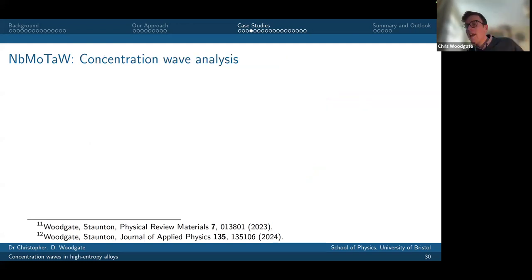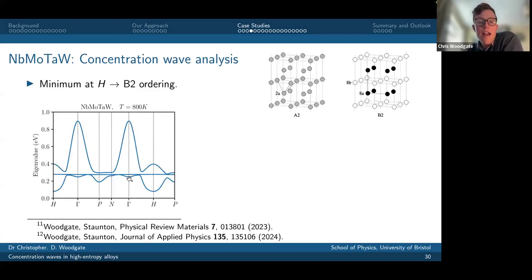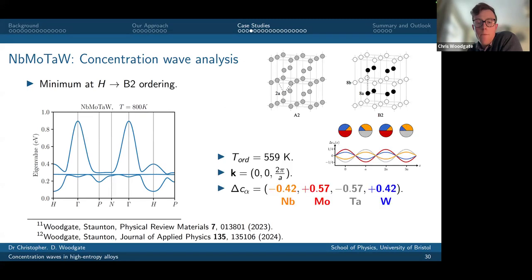If I do my alloy S2 theory, my concentration wave analysis, I find that my minimum eigenvalue is occurring at the H point, and that is indicative of a B2 ordering. So going from the disordered BCC solid solution, A2, to the ordered B2 structure, which is two interpenetrating simple cubic sublattices. And if I apply the Landau theory, my ordering temperature is estimated at 559 Kelvin. This wave vector, 0 0 2π over a, that's the H point.